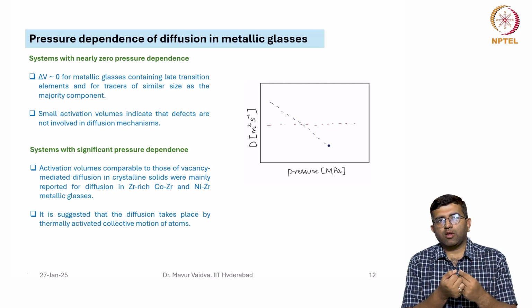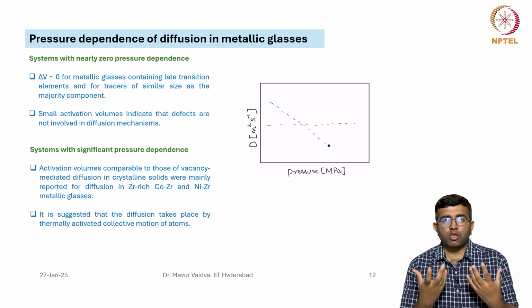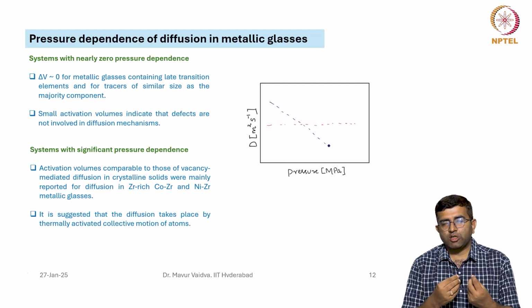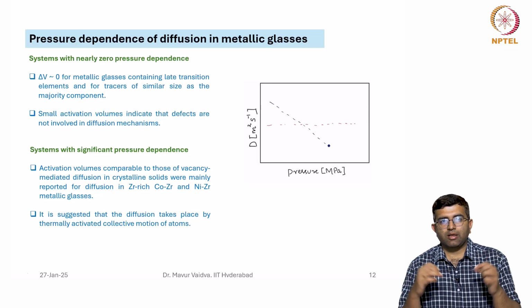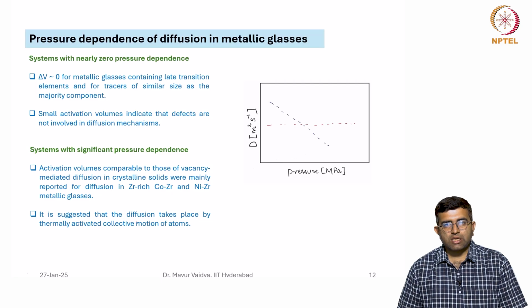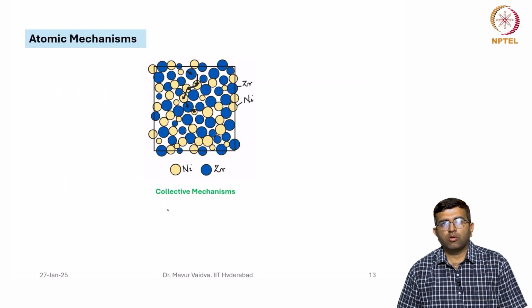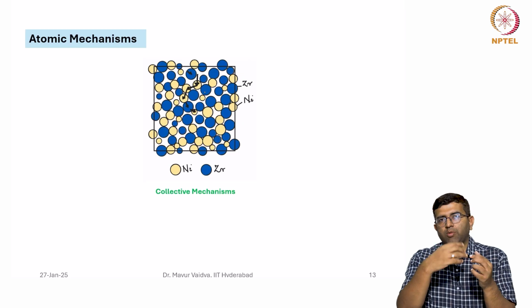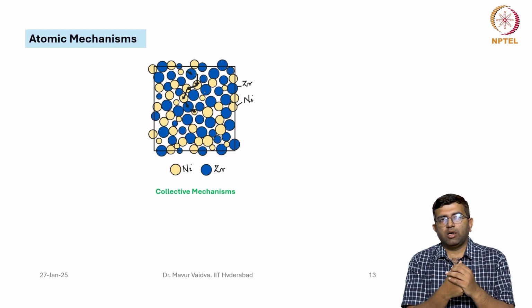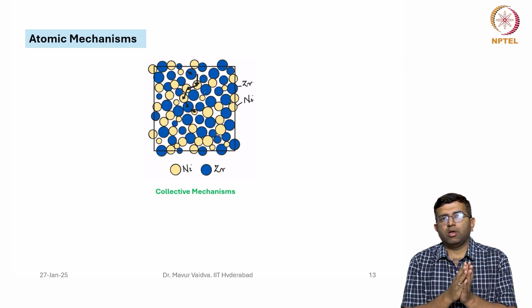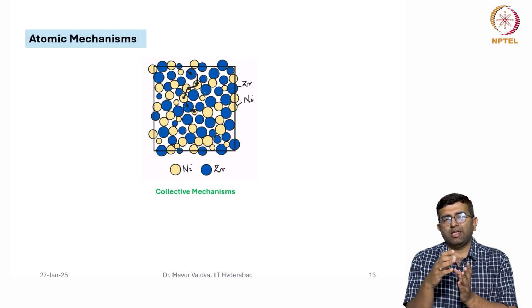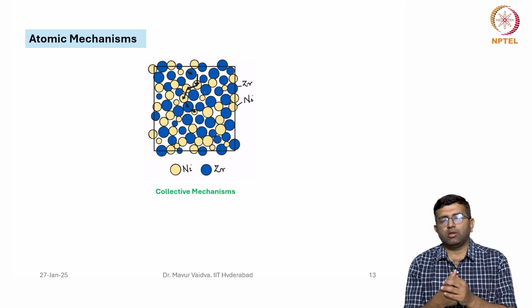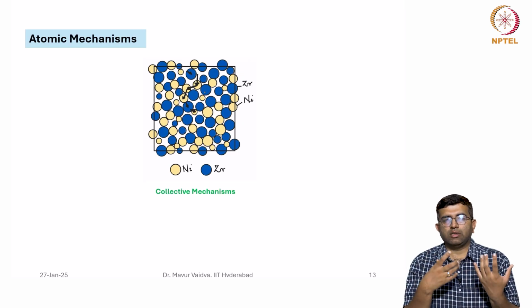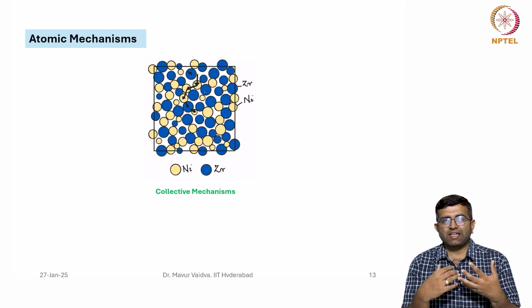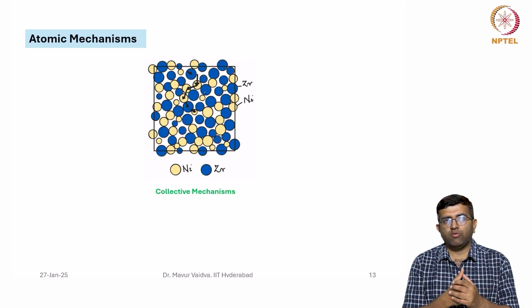Remember, in these kinds of special materials, many times computational techniques are used to understand the mechanisms, because it may not always be possible to perform the experiments in the correct manner. What has been suggested is that diffusion takes place by thermally activated collective motion of atoms. So one atom doesn't move, like we saw in conventional metallic alloys or crystalline solids, where one atom exchanges with a vacancy. In intermetallics, we saw that two defects are involved. Here, what is believed is that the diffusion involves a collective motion of multiple atoms. Then only can the diffusion occur.